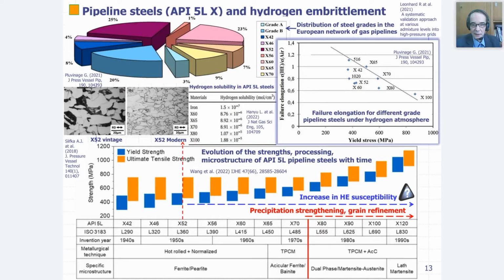As you can see on the diagram, for failure elongation from different grade material, it is obvious that failure elongation, which is a measure of the plasticity, drops significantly in the case of high strength steel. As you can see, ultimate tensile strength rises with the modern steels, and we have a sharper drop of failure elongation in the case of X100 in comparison with the older, more ductile and lower strength steels like X42 or X52.